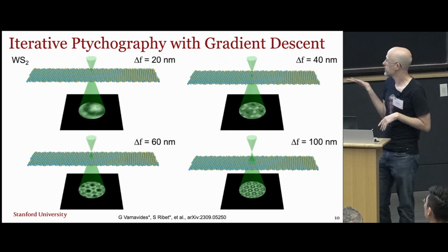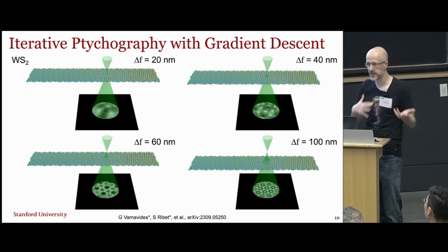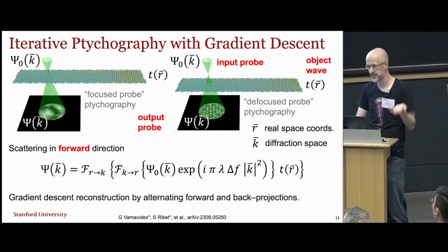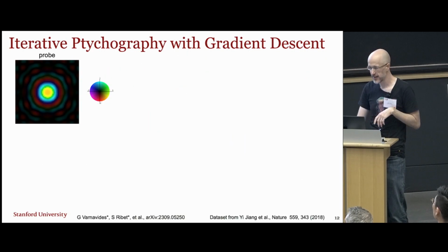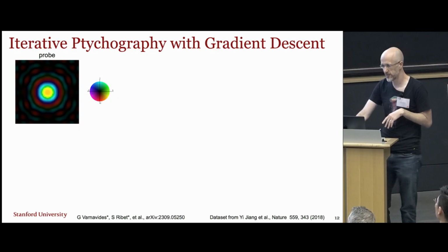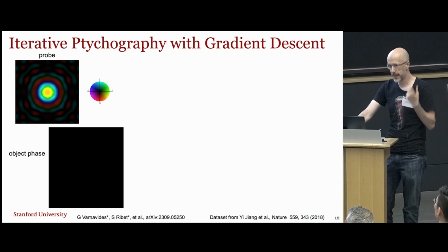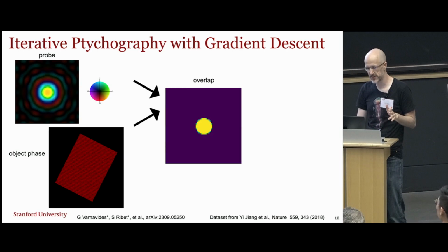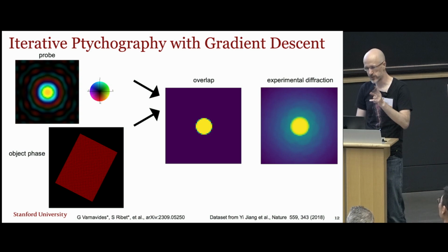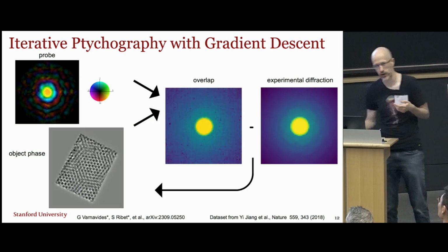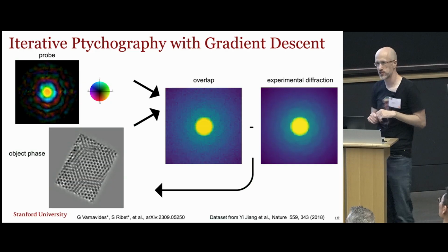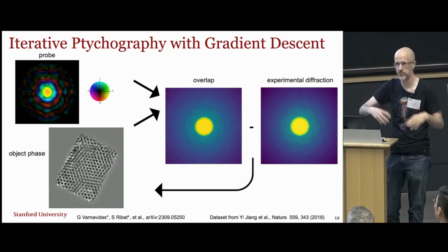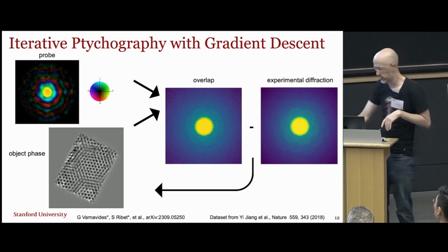So ptychography, of course, we scan over the sample surface, often with some defocus, and then we use the redundant information in overlapping probes, and we can use this plus some forward physics to reconstruct the sample. So just showing pretty much the exact same thing that Pinchane showed, a guess for the initial probe, the empty object that we start with. We calculate the forward scattering at each of those red dots. That's the probe positions. We compare that to the experiment, measure the difference, and then simply back propagate using the adjoint operator. And within about 5 or 6 iterations here, you can see we converge on this much, much sharper image. And the probe itself has become aberrated because we're solving and fully deconvolving for those aberrations.